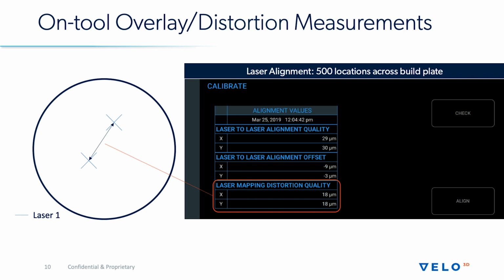In addition to doing the overlay test, it also allows you to do a distortion test where it's comparing where the pattern is being generated for one laser relative to itself as a function of how far away the two objects are from each other. And the standard deviation of that particular error is then given by the distortion quality. So this is something that you can check before or after any given build with an automated routine by just clicking a button on the system. And if anything is out of spec, you can always align it in real time using the same screen.